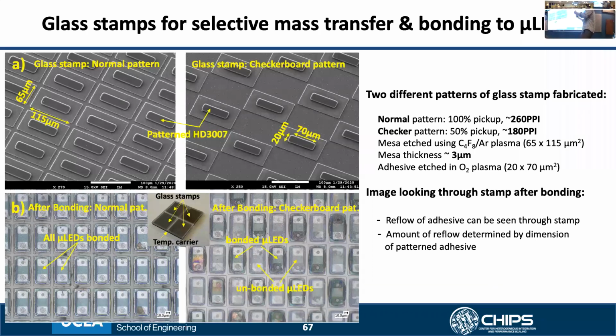Next, we do our mass transfer using the glass stamping process. The top SEM images show a fabricated glass stamp with the patterned adhesive on them. The left side is a normal pattern where every LED is picked up, and the right side is a checkerboard pattern. The adhesive is also lithographically patterned on these glass mesas, so as to control the amount of reflow that the adhesive has during the bonding process. The optical images on the bottom show the samples looking through the glass stamp after bonding it to the LEDs sitting on the temporary carrier.